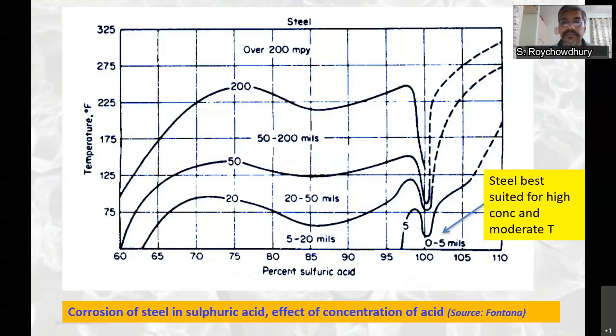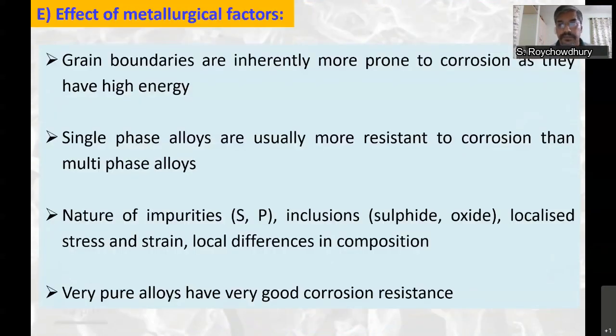If you see in this figure, this is an isocorrosion chart. At very high concentration of sulfuric acid, in excess of 95%, the corrosion rate is very low, around 0 to 5 mils per year, if the temperature is not very high. So carbon steel is used for storing sulfuric acid as long as the acid is highly concentrated and it is not contaminated with any water or moisture.